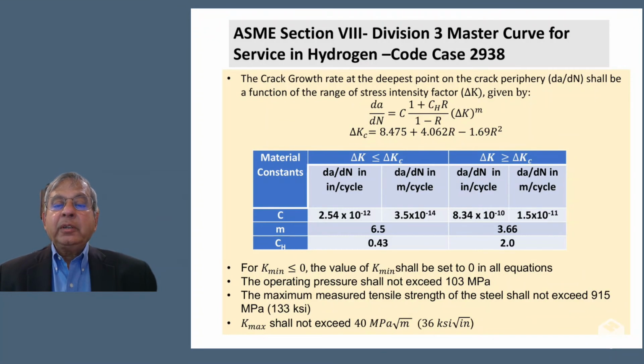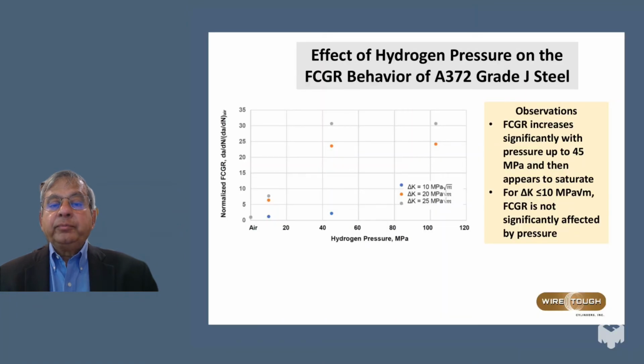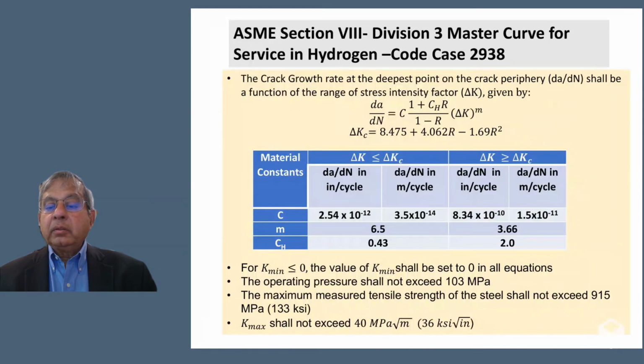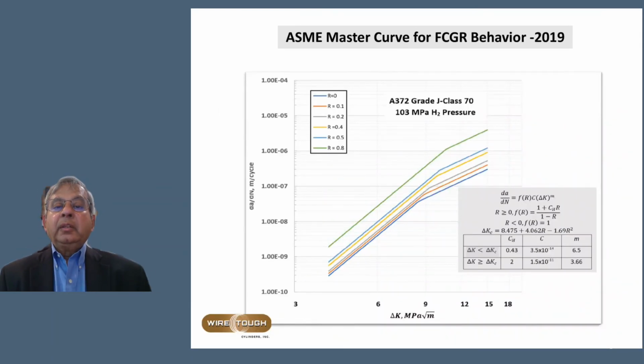And we see a transition behavior in which, beyond a certain delta K, the crack growth rate curve slope decreases significantly compared to when the delta K is less than that transition delta K. And all this is very evident in this plot here that shows how the da/dN changes with delta K as a function of various load ratios ranging up to R of 0.8. You can see that in each case there is a delta K level at which this transition occurs. And when you go to R of 0.8, for example, the transition occurs at a much higher delta K than it does when the R is equal to 0.1 or less.